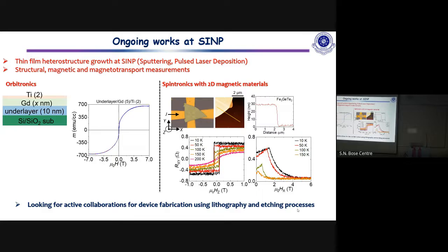So when you have this kind of signal, how do you know that there is a spin texture involved? So we did this concomitant measurement where we measured the Hall and also the magneto-optic at some particular magnetic fields, and then we see that it matches with the image, that there is an existence of a spin texture. But you apply electric field and magnetic field in the same direction. Yeah, this current density is very small. So the current density, in our understanding, is not causing any effect on the magnetization.